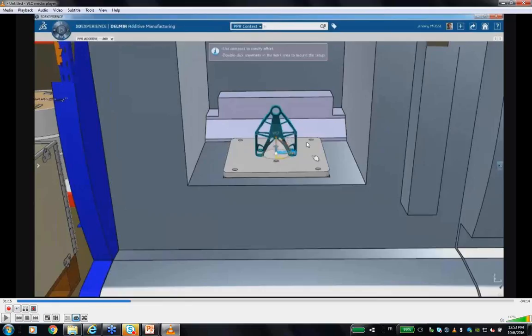Typically here, this area has an angle which is almost 10 degrees or 20 degrees according to the printing direction, and we need to create support areas here. Okay. For here, of course, there is no support area because it's almost vertical. So we need to optimize the position of the part on the tray to minimize the support and also to minimize the height, because the printing time is depending on the height of the part on the tray. And of course, the finishing time is depending on where the supports are.